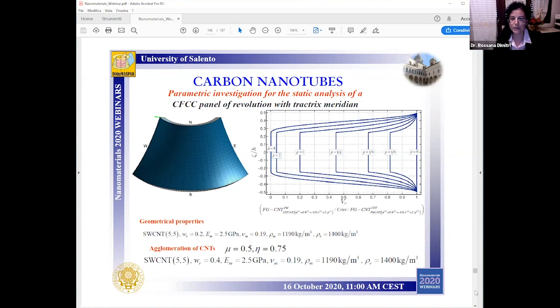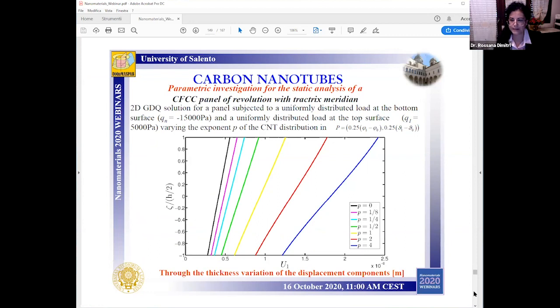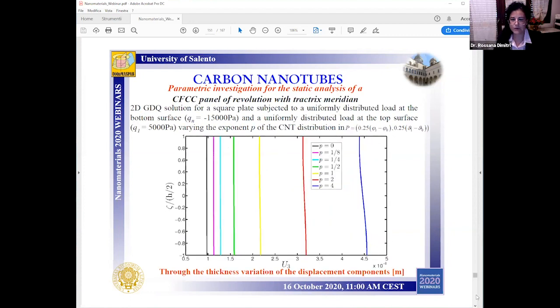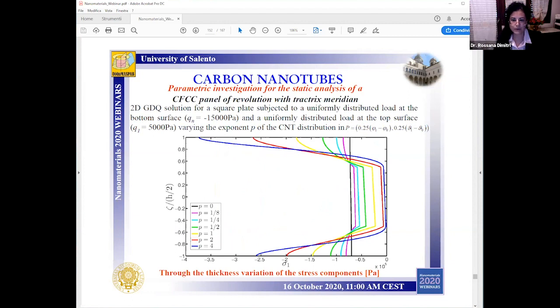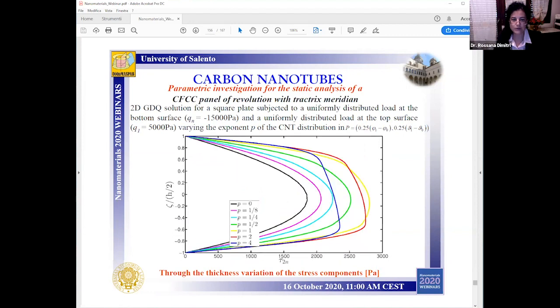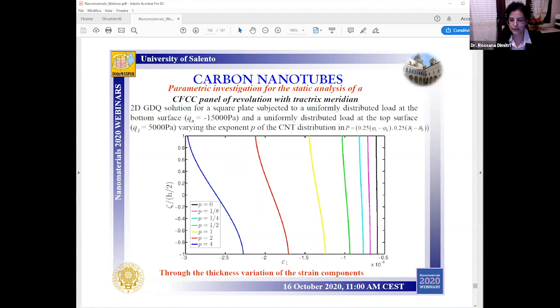So once again, we compute the displacement, stress, and strain profiles at a fixed point as a function of the exponent P of the carbon nanotube volume fraction distribution at both external layers. And here we don't include the Murakami function in the model since the soft core effect is in this case negligible. Look also at the variation of the response, where the case for P equal to 0 corresponds to a structure uniformly reinforced by carbon nanotubes. And here are the other displacement components. And also have a look here at the smooth variation throughout the thickness, also for the stress components, as well as for the strain field, which is also highly affected in its variation by the selected power values.